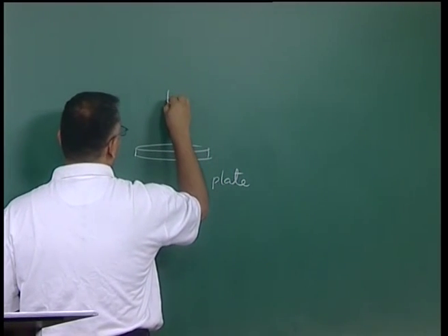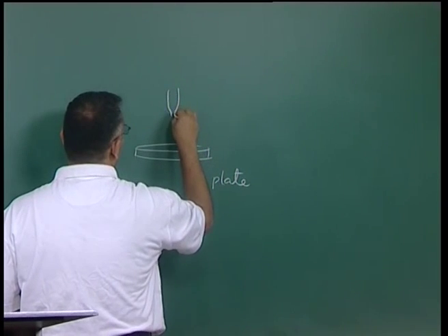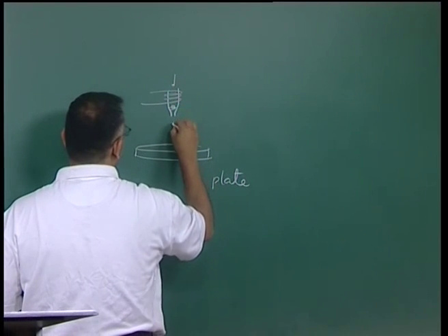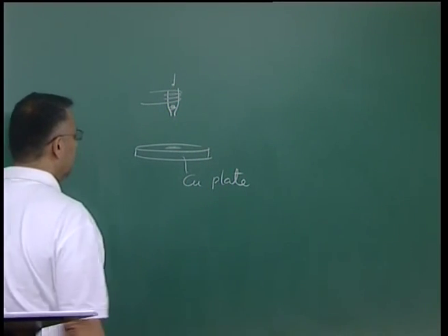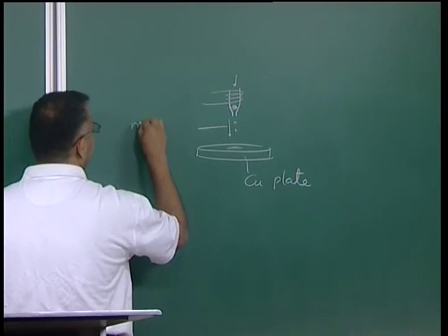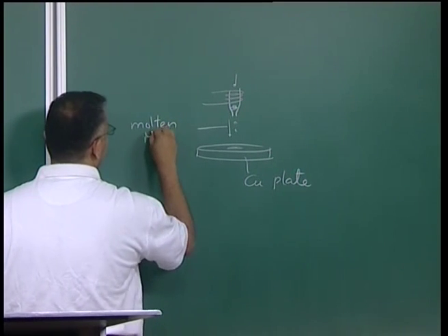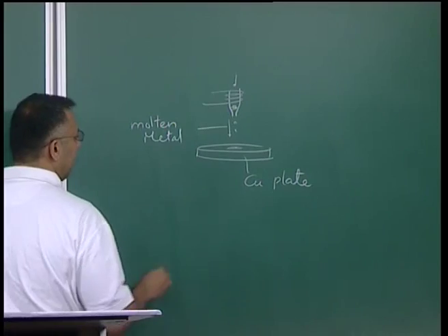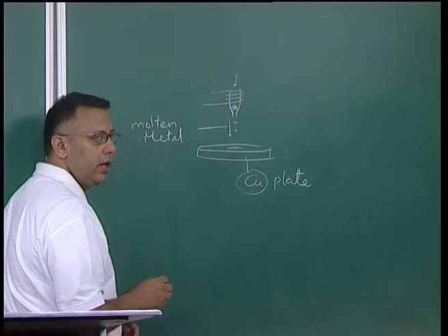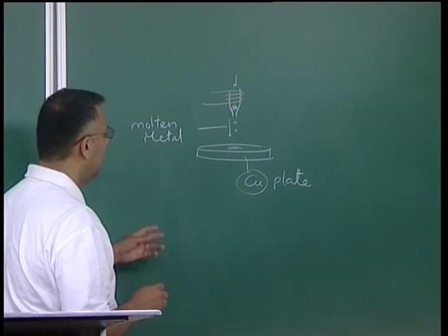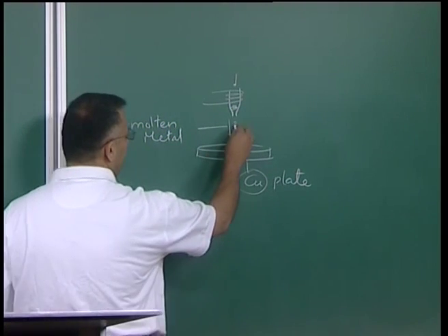And you can put a molten pool of material. For instance, you could melt some metal using induction and purge it with argon, and this molten jet could fall on the substrate and get flattened out. So when this molten metal falls on the substrate of copper, for instance, which has a high thermal conductivity, very high cooling rates are experienced, especially by the initial surface which is falling on the substrate. And since the amount of metal being put here is very small, typically most of the metal feels a very